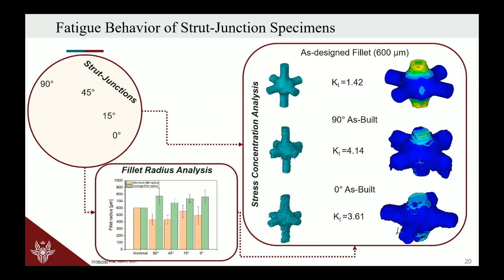And after that, we also studied the junction, which is the critical point. So the node is always a critical point for fatigue issues because we have the variation of the geometrical features, and there you have the maximum of the stress concentration factor, and there you have the initiation of all the cracks that are affecting the final failure of the lattice structure.